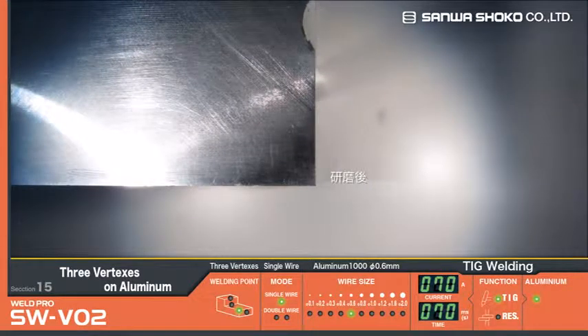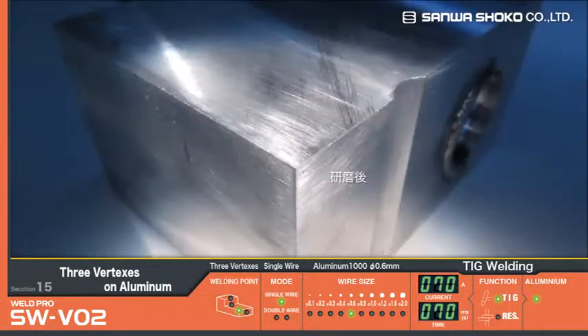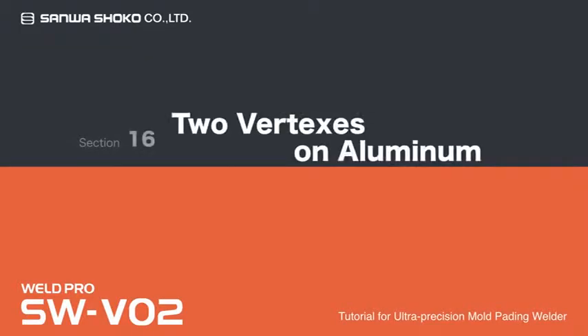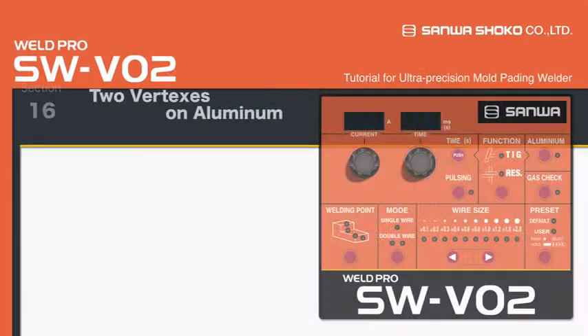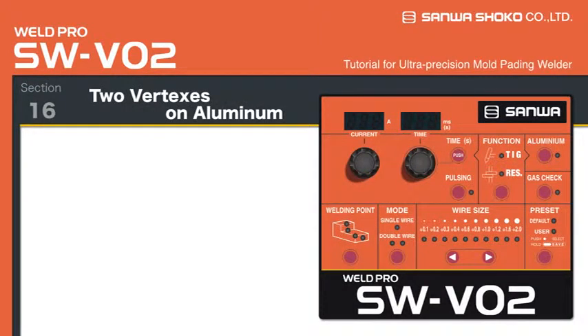Even though the welded area is polished, it can be confirmed that no shrinkage is observed. This is the completion of the repair with no shrinkage in 3 directions. Now, 2 vertices are welded in the aluminum mold.